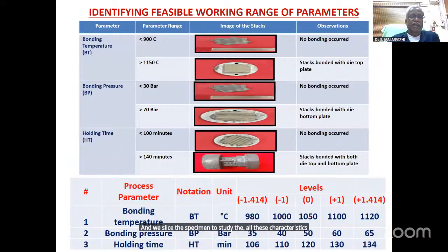And it's not easy because first we have to identify the feasible range of temperature. So less than 900 degrees centigrade, no bonding has occurred. And above 1150 degrees centigrade, stacks bonded with the die top plate. Okay, that is the problem. So in between 900 to 1150, quality bonding we achieved.